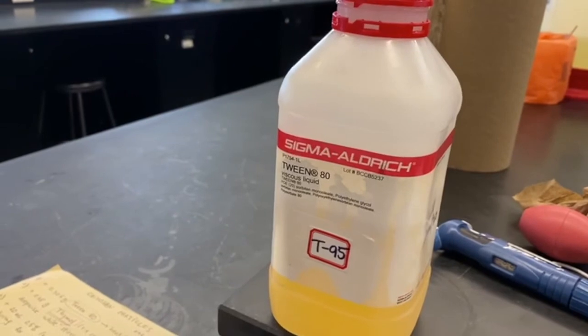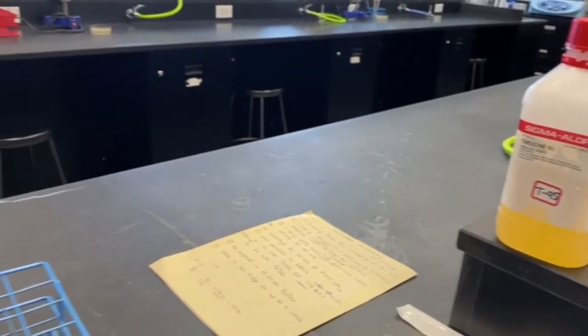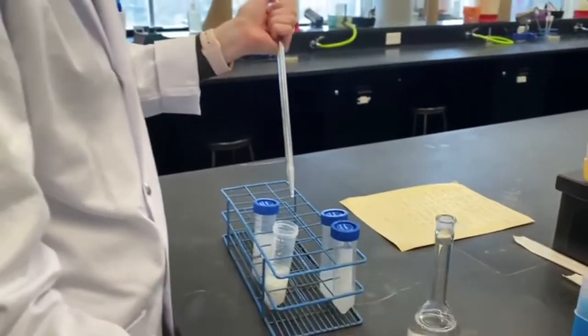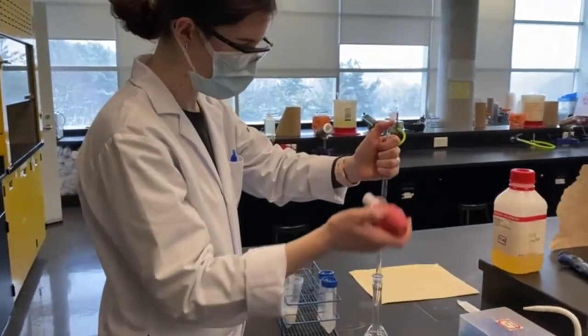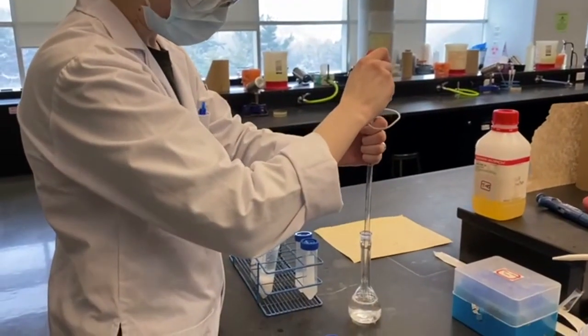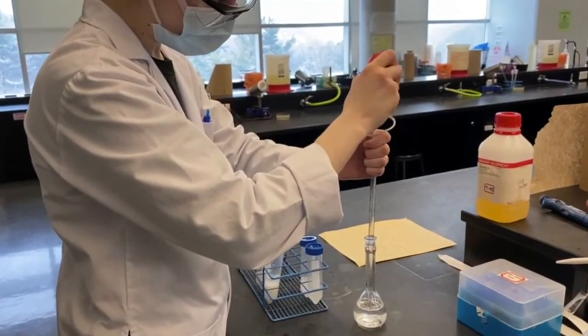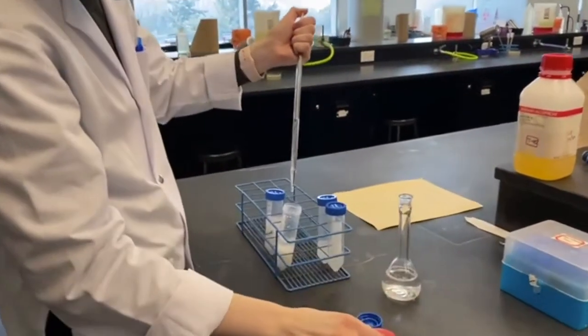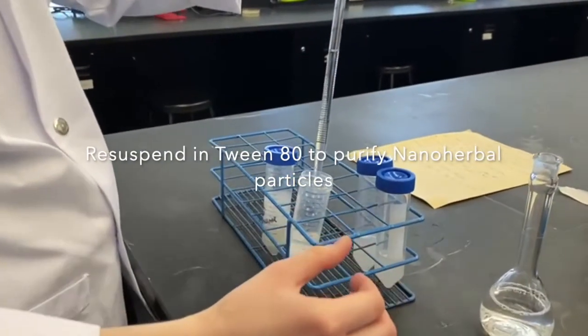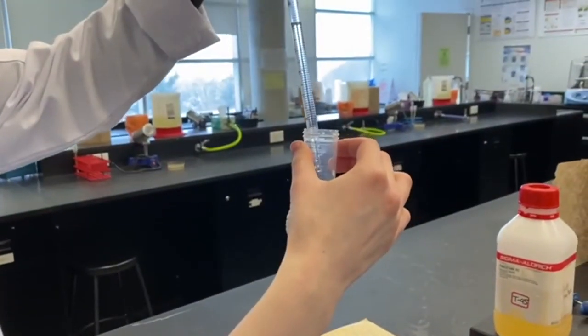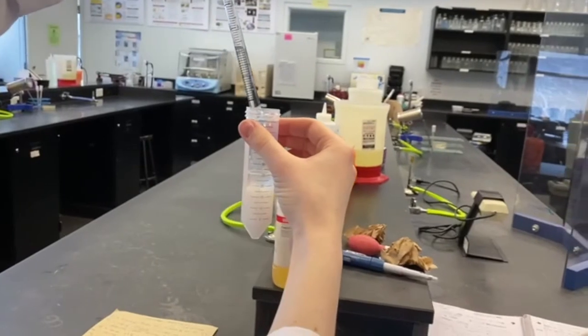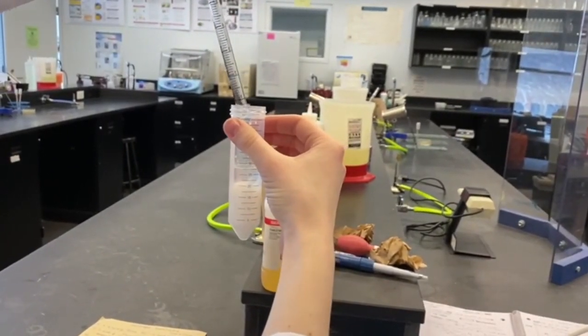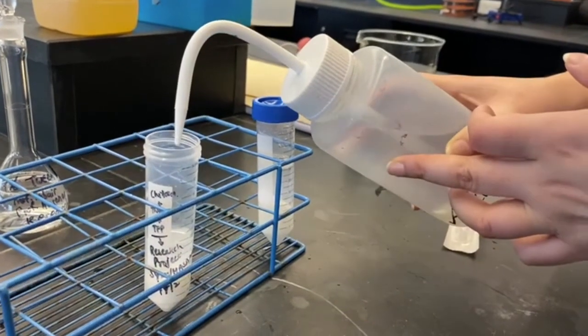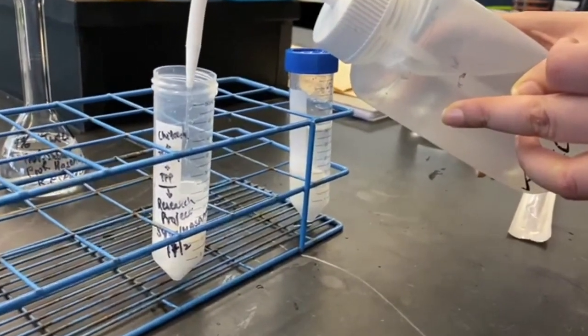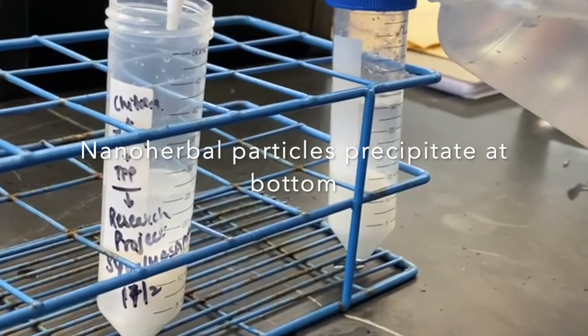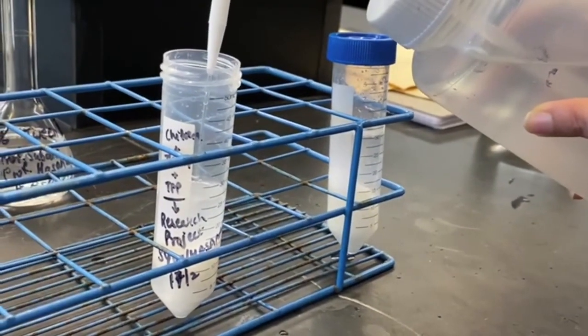So now when we have separated the supernatant and the precipitate, we need to resuspend it with the solution of Tween 80 with distilled water in order to purify our nanoparticles even more. And afterwards we will vortex it and we will centrifuge it again. Okay, so now we want to wash our precipitate twice with the distilled water, which we have already cleaned with 1% Tween 80, to get a nice and clean precipitate at the end.